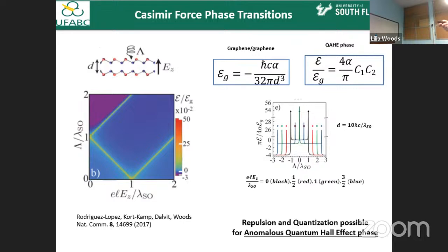I would say that the most curious one is when the two interacting materials are in the quantum anomalous Hall effect phase, where the interaction energy is proportional to the product of the two Chern numbers. Because the Chern numbers could be positive and negative, the product could be positive and negative, and that is interesting. The other interesting, kind of discouraging, thing is that the interaction between two graphene layers in the asymptotic regime is proportional to the fine structure constant, alpha, and it's universal. So the two graphenes interact in proportion to the fine structure constant, but the two materials, if they're in the quantum anomalous Hall effect phase, are evenly matched, because the interaction is proportional to the Chern numbers.